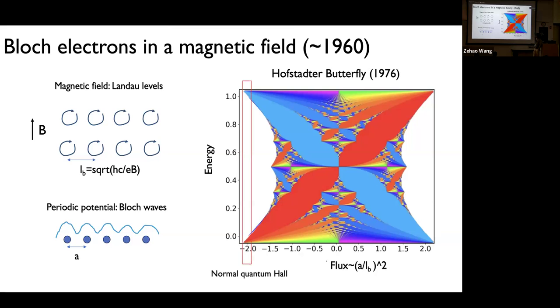But one key issue is that for most of the materials that you have, you are on the left-hand side of this axis. The reason is that in the crystals that we have, or the thin films, say gallium arsenide, the lattice constant is of the order of angstroms, less than 1 nanometer. And if you want to go to this colorful region, where colors change very abruptly and frequently, you actually need thousands of tesla of magnetic field, which is not achievable, at least with current technology. So if you cannot change the magnetic field to compensate, but you still want access to this colorful region, what you can do is find ways to change the lattice constant.